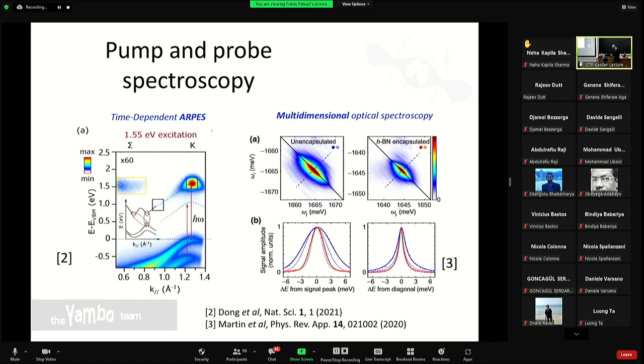Okay, so in general, it's kind of a bad idea to try to apply Bethe-Salpeter to metals, exactly because of the screening problem. Metals are very heavily screened, they do not have a gap, and dynamical effects in this screening are extremely important, while here the way we are treating electron-hole interaction is just at the static level. So most likely, if you try to do that, you will get wrong results.